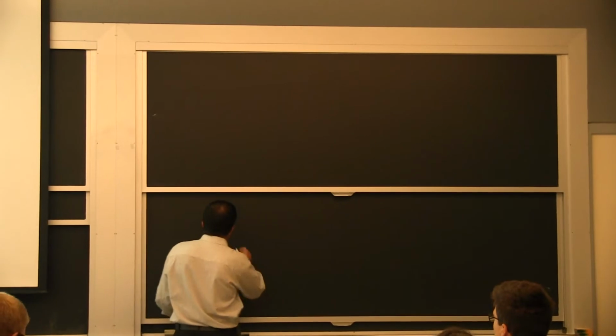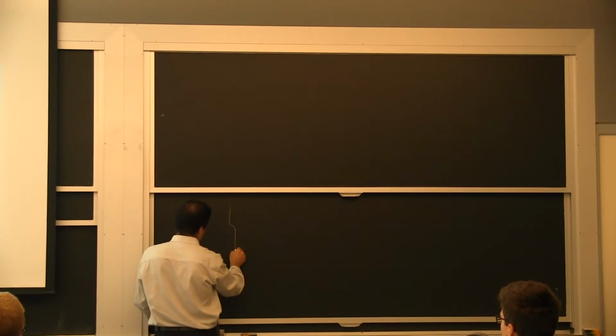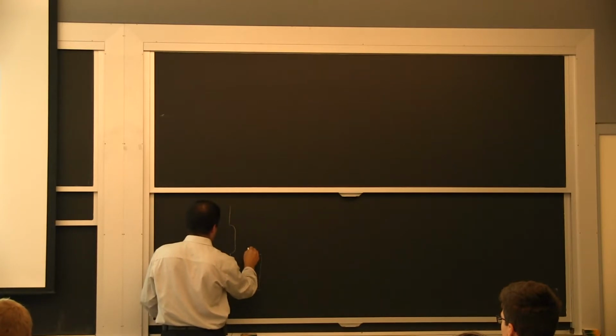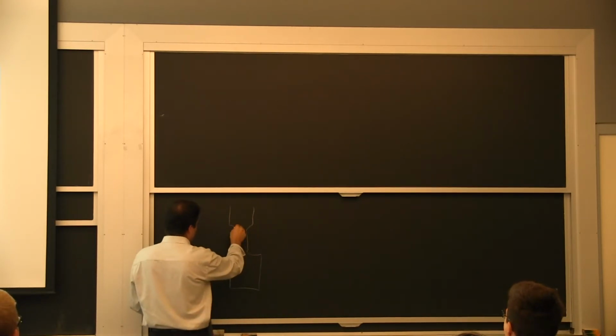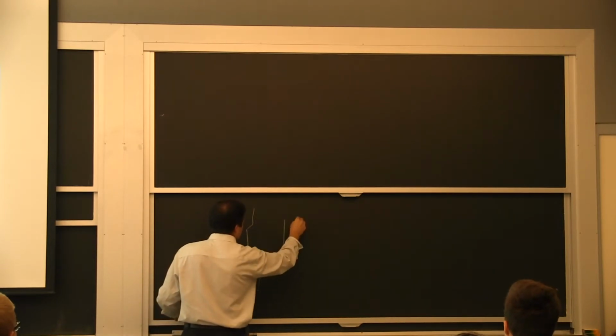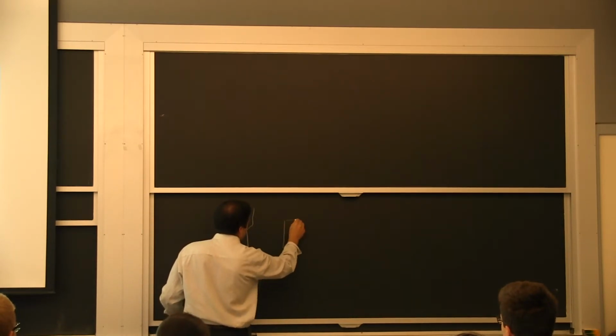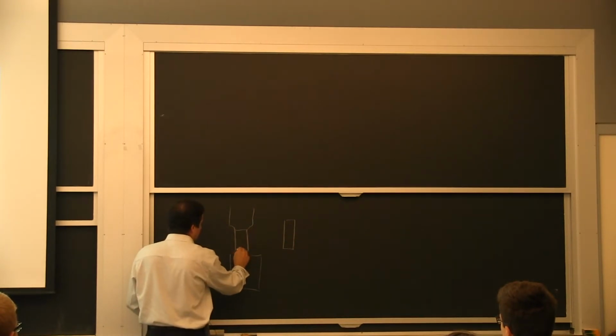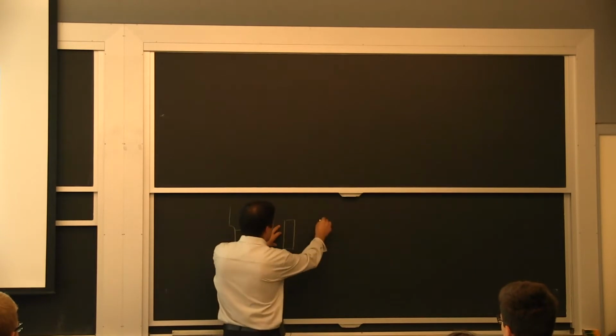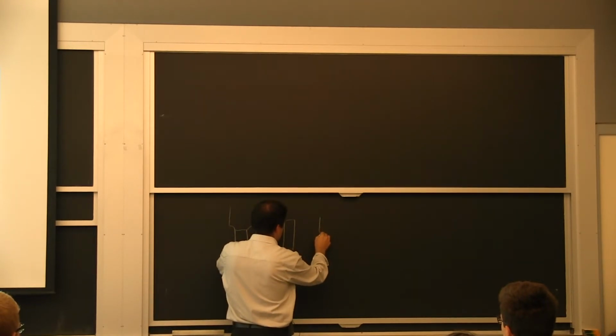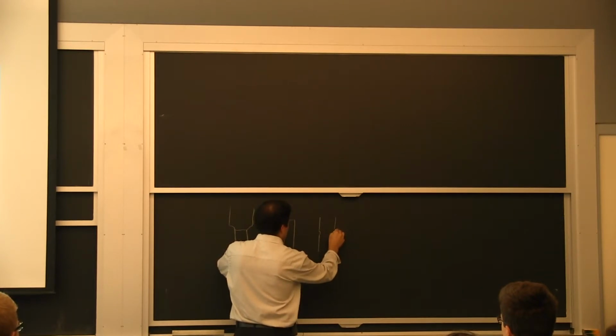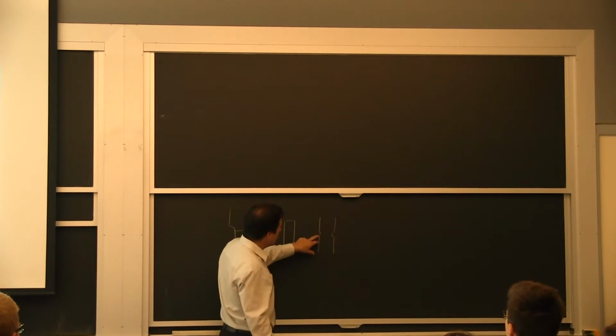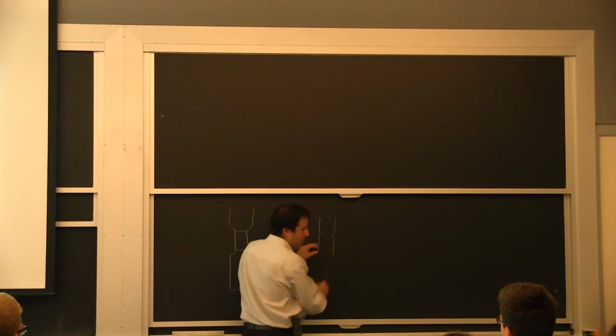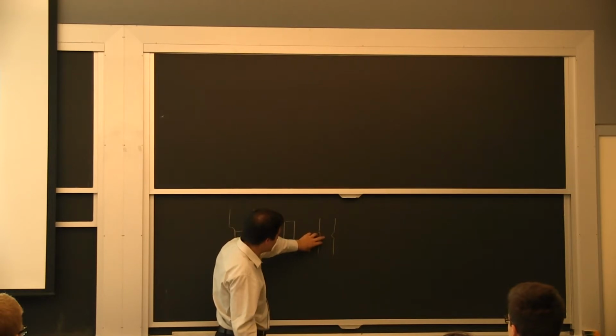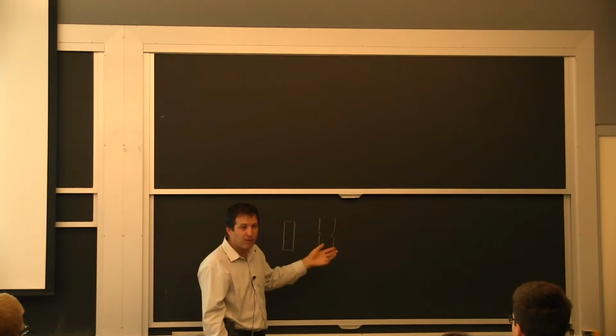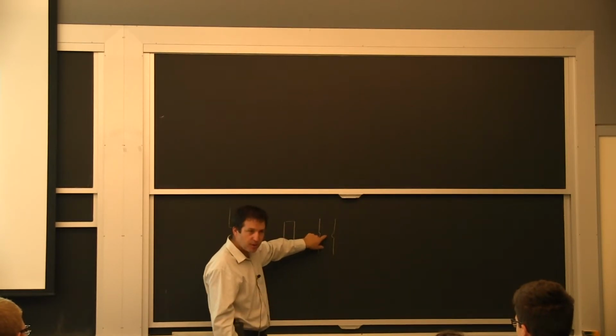With a round specimen, say if I pull on it, I got it machined, and everything is going on very nicely at the beginning. It's all deforming homogeneously, so it stretches to say this. We're at 20% elongation. We started here with our gauge length, we're at 20% elongation, and then we start forming that neck. So it's reduced in area here, and when you look at it on a plane, eventually it will snap. And typically, you can get to a local area that's about half of what you started with as the nominal area, exactly where the crack